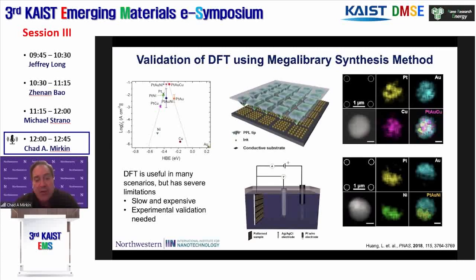Okay, what about catalysts? How do I do that? How do I think about that? I think about it in two ways. One is I can work with theoreticians that look, for example, at the early libraries we make and say, which of these materials might be interesting from a catalytic reaction standpoint? We did that with Chris Wolverton. We were asking the question, could some of these be active with respect to the hydrogen evolution reaction, where platinum is king and you're trying to beat platinum? And he can, in computero, construct a volcano plot like the one on the left and begin to look at which of the materials that we've explored should interact well with hydrogen and might be good candidates for the HER.